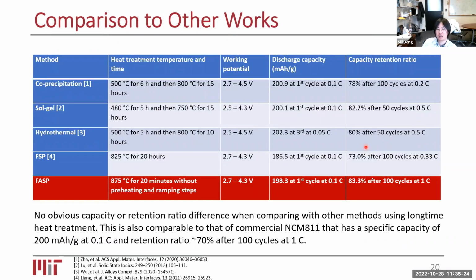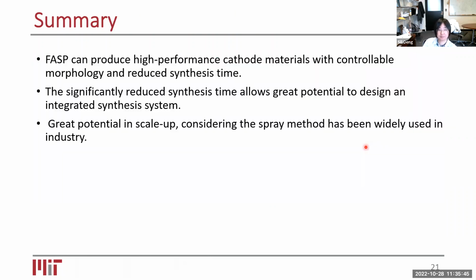And compared to the literature, essentially we can achieve comparable performance no matter which wet chemistry method or flame spray pyrolysis method they use. We achieve comparable performance, but we can significantly shrink the time needed for the particle synthesis. So the partial summary for this first part is that we can really control the entire temperature history that a precursor experiences to form particles. And this turns out to be very important to control the morphology and performance of the battery materials. And with this shortened synthesis time and simple geometry, simple equipment, we do see great potential for the scaling up of this technology to be widely used in the industry.